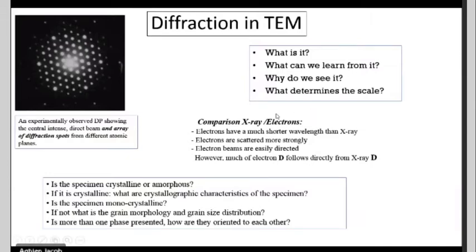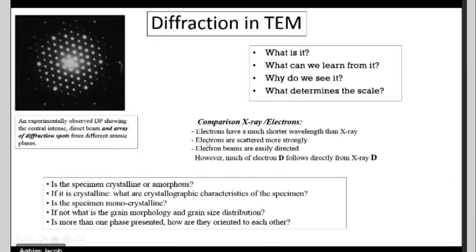We use this electron beam because electrons have the shortest wavelength compared to X-rays — in the range of picometers, depending on the accelerating voltage. We can go to a minimum of a few picometers of wavelength, giving us a large Ewald sphere and more extractable information. Electrons are scattered more strongly compared to X-rays and neutrons. Electrons can be scattered by electron-electron scattering (smaller scatter angle) or by the nucleus (larger scatter angle). Today we will focus only on the analysis part.